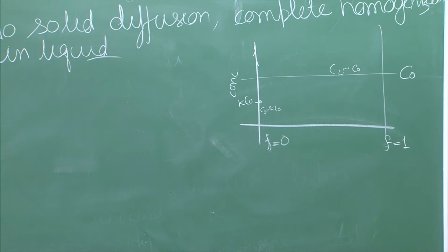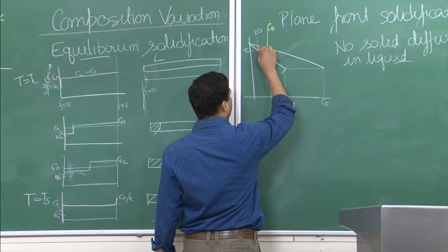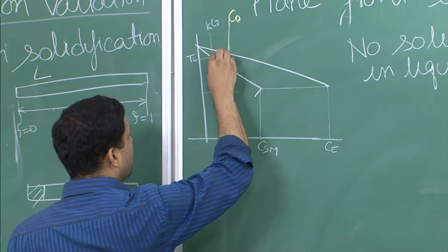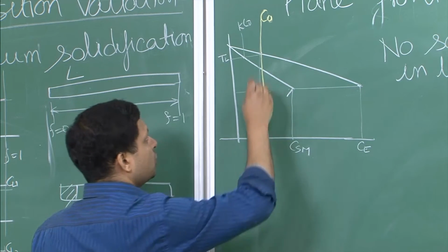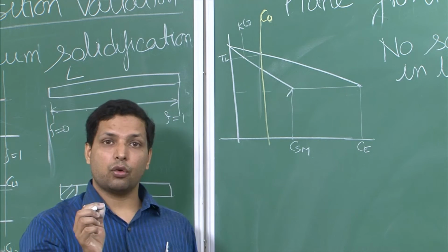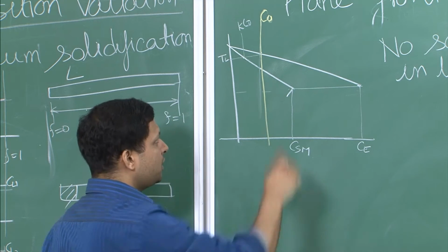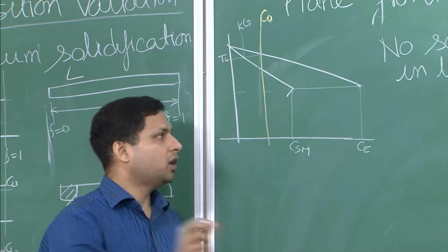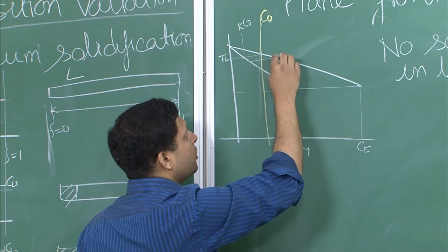Now what happens next is very different from what we discussed earlier. Over here when the solidification starts to take place, the next solid that forms is over here, but this is only the outer layer of the solid which has this concentration. So the solidification of the outer layer goes like this, like this, like this, but not the overall concentration. When we are looking at the phase diagram in equilibrium condition, what it says is that at this particular temperature all of solid should have this concentration, not just the outer layer. At this particular temperature and for this concentration, all of liquid should have this concentration.